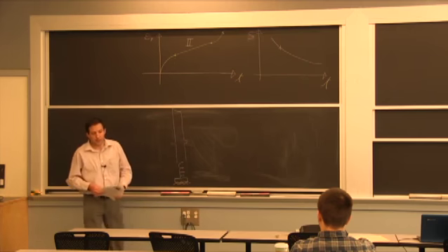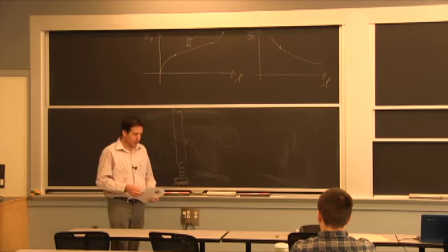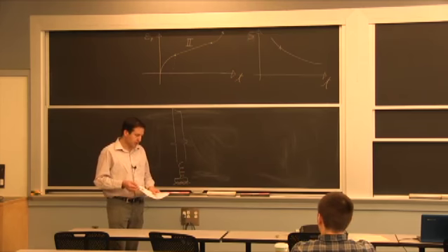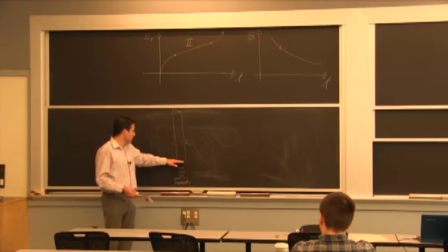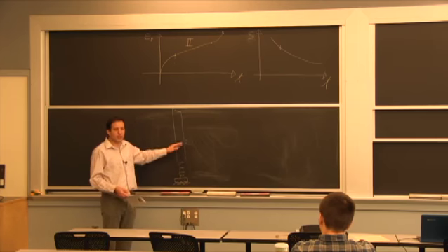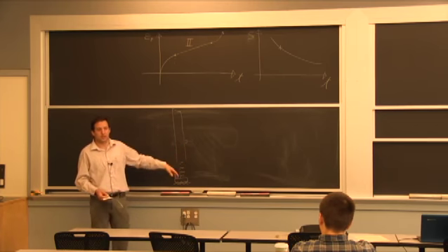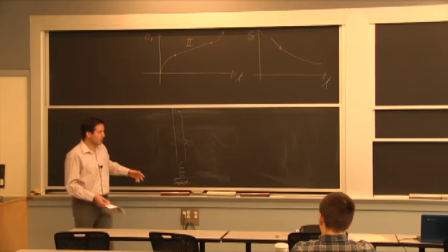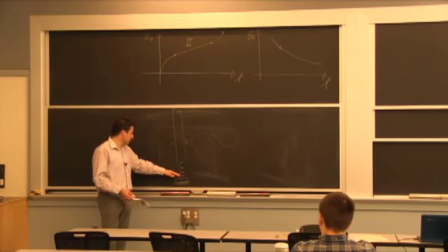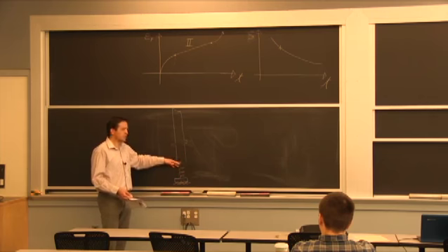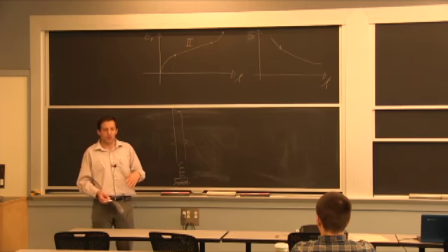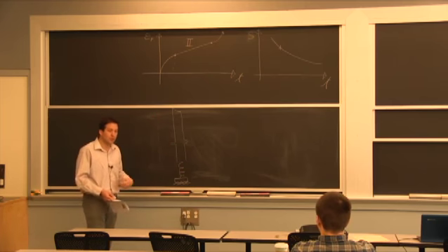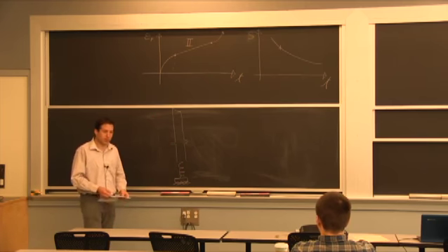There are issues with alloying. So some alloys will essentially, as you solidify, try to push back the alloying element in front of you because it's harder to fit them in the solid than in the liquid. So you have to set your speed so you don't give it the chance to do all that separation. You want to have it homogeneous. There's only so slow you can go and make this work correctly.